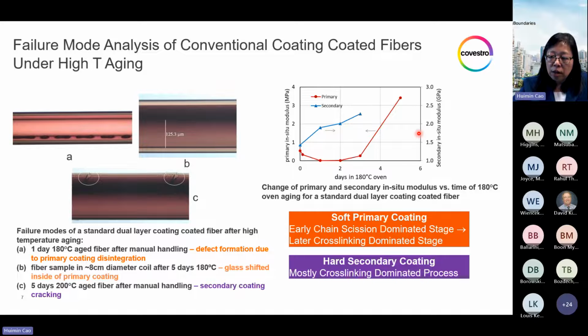And even when the material turns harder at a later stage, you should not consider this a recovery of the coating properties, because this aging-induced cross-linking occurred after a severe transition when the network was already destroyed. The termination process forms very short chain crosslinks, resulting in a very fragile material. Let's look at the secondary coating, the blue line. The secondary coating did not show a transition-dominated stage. The modulus rises and elongation decreases with aging, which leads to embrittlement.